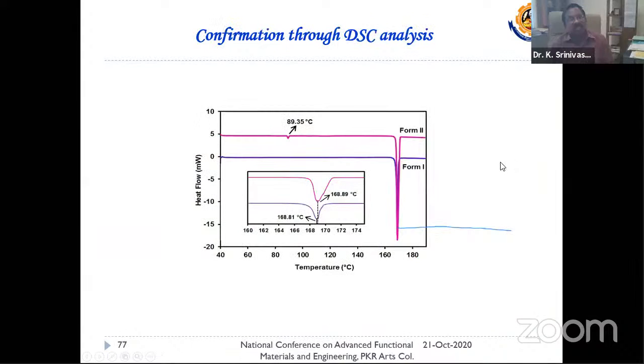Another confirmation is the differential scanning calorimetry, with which one can find out the phase transformation from one form to another form. Whereas the mono form doesn't show any polymorphic phase transformation till its melting, the form 2 ortho, since it is metastable, shows an endothermic peak well before the melting. So after investigation, we found that there is a phase transformation from form 2 to form 1 here. It is yet another confirmation, above ambient conditions. Another confirmation for these polymorphs.